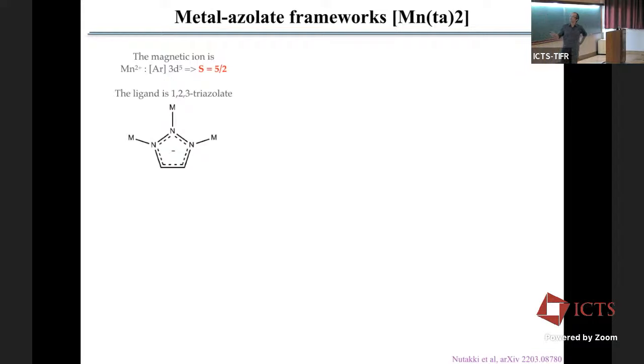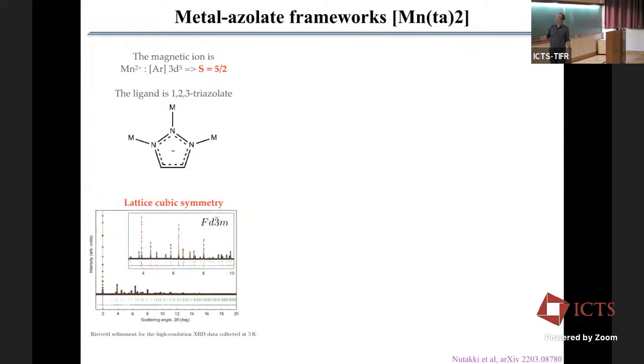Then the ligand between them connecting these manganese ions is made of 1,2,3 triazolate, like this. So I will show you the 3D structure in a moment. Our colleagues have done high resolution X-ray diffraction to measure the symmetry of this lattice, and they have found that we have a lattice cubic symmetry.